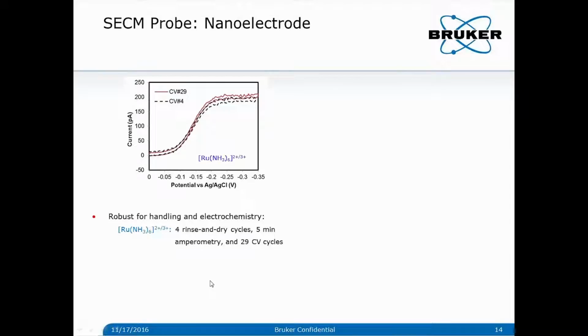As a nanoelectrode, we also tested its electrochemical performance. This is a cyclic voltammogram of the probe in a ruthenium hexaammine solution, and the sigmoidal, or S shape, of this curve is very typical for nanoelectrodes. You can see that in the non-faradaic region, it has negligible leakage and capacitive current. That demonstrates a very high quality insulating coating of this probe, and the probe design is robust for handling and electrochemically stable.